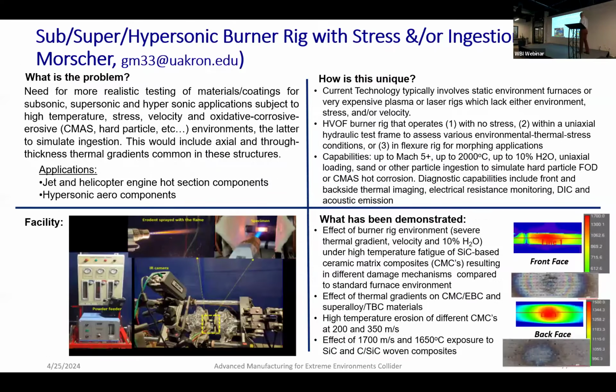So this is probably the coolest thing we've got in our lab. This is a burner rig. It is an HVOF flame, high velocity oxygen fuel. We've got a couple different nozzles. We can go from about 200 meters per second up to over 1,700 meters per second, so we exceed Mach 5. We can go from about 800 C up to 2,000 C. So we have that whole range. Really, this is geared at sub to super to hypersonic hot section components.